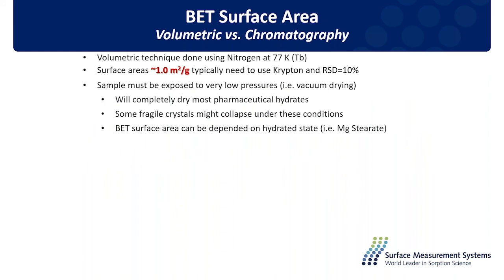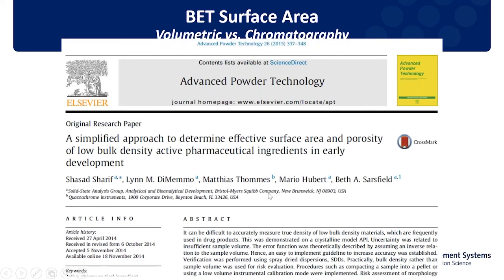So that instrument is not that suitable for low surface area materials, and also there's vacuum, which can affect structural properties, besides the temperature, because so many pharmaceuticals have a low glass transition temperature point. So when you cool down that solid to the measurement conditions of volumetric measurement, you are going through the glass transition point, and basically at the end you measure a solid which is structurally different from what you wanted to measure. There's a publication on this, and an interesting fact about this publication is that one of the authors was from Quantachrome.